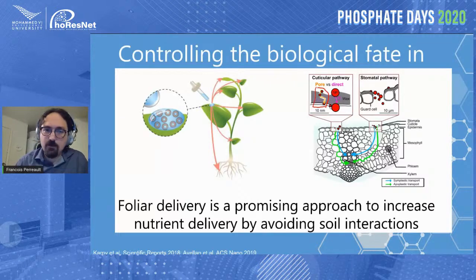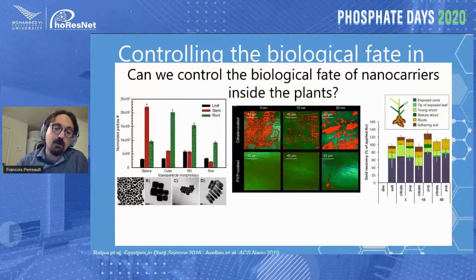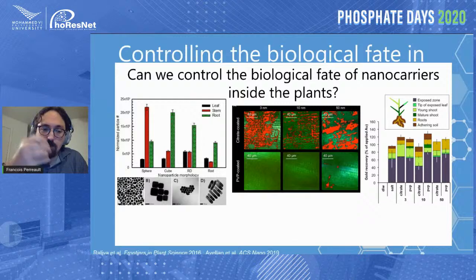So that's a way to avoid all the soil interactions, avoid the leaching and the erosion and the competition with microorganisms, because now you're feeding your chemical directly into the plant. The main question when you apply foliar delivery is, does it stay in the leaf? You don't want that. But nanotechnology has found that you can control where the particle goes in the plant by changing the size, the shape, and the surface chemistry of your particle.